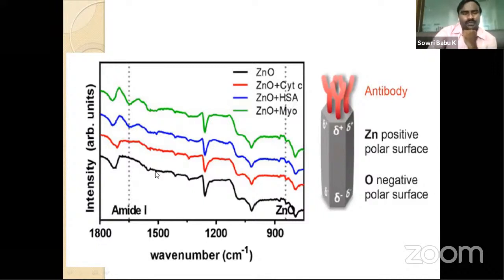So we prepared a solution with these proteins, and we immersed our zinc oxide nanorod platform in that solution for 24 hours, and then we measured the FTIR spectra of those nanorods after taking them out from the protein solution.